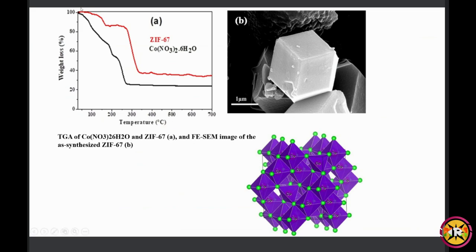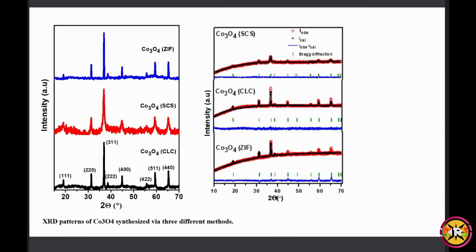So I have done TGA to check the thermal stability of cobalt nitrate and ZIF-67, and as you can see, the cobalt nitrate decomposes at around 300, and ZIF-67 at around 350. So from there I chose the temperatures: ZIF-67 I calcined at 450, and cobalt nitrate at 350. And finally I got this kind of normal spinel structure of Co3O4 in the different synthesis processes, and this is the same image of ZIF-67. So now coming to the characterizations.